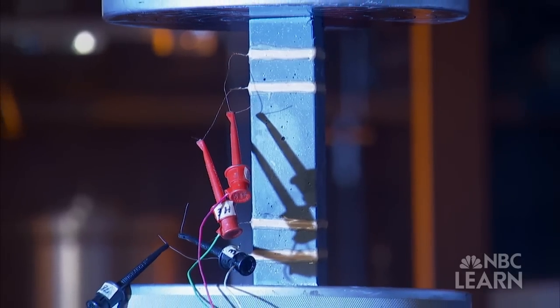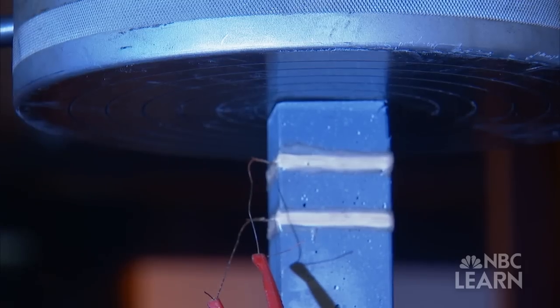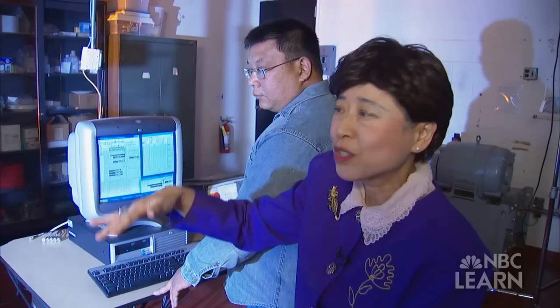As this experiment demonstrates, by attaching a meter to a sample of concrete, Chung can measure the precise amount that the smart concrete deforms as a hydraulic press clenches down on it. "We are increasing the amount of deformation step by step, and that's why the resistance decrease, which occurs every time we compress."